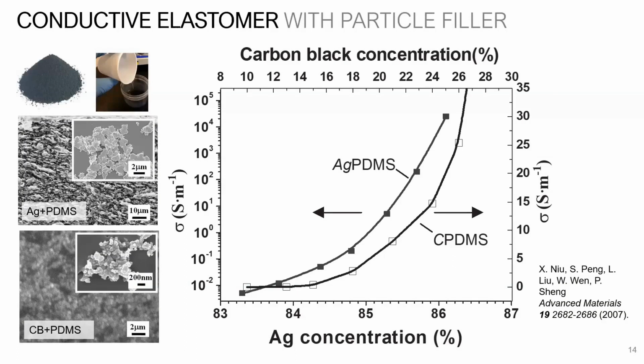So it's well known, of course, that if you just take the silver by itself and blend it with PDMS, you can achieve very high electrical conductivities. Again, it requires very high volume fractions, very high weight percents. In the case of just silver alone as a filler, as a lot of you probably have experienced, these high weight percents also make these materials quite brittle. And when you start stretching the materials, you start degrading that percolating network, and you lose electrical conductivity. So good for flexible circuits, but not really great if you want very robust, highly stretchable electronics.